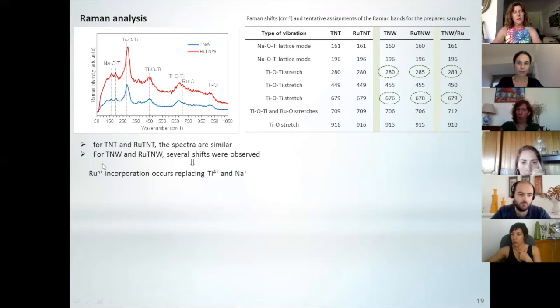And what we discovered is that for titanate nanotubes, the spectra are similar. We have here the vibrations, they are exactly the same. When we look at the nanowires, we have some changes here, okay? So we have some shifts in some of these peaks.